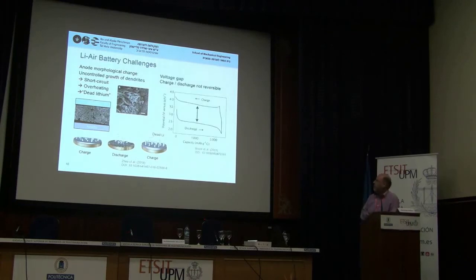Another problem is that in order to charge the battery electrically, we need an overvoltage, and we see here that the overvoltage is actually huge. So this is already a penalty in efficiency of about 40% or something like that. So this is not really practical.